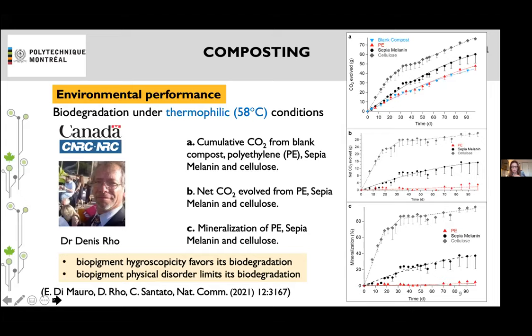So here I show you, just rapidly, the results of an effort we made in collaboration with the Canada National Research Council, with microbiologists, on the biodegradation in industrial compost conditions, following the industrial standards, in this specific case the ASTM D5338. So we follow the evolution, the mineralization of the melanin, comparing with a negative reference that is polyethylene and a positive reference that is cellulose. And actually we observed that even if, for the standards I was mentioning, we cannot consider melanin a compostable material, still we are behaving much better than the polyethylene, not so well as the cellulose, but much better than the polyethylene.